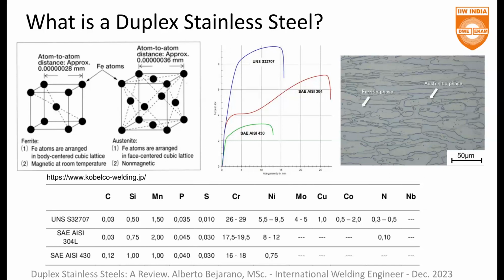And in blue, we have a hyper duplex stainless steel. So we can see here that we have a higher strength in terms of the tension resistance, the ultimate strength. But the percentual elongation is not the best. It's more related with the ferritic stainless steel than the elongation of austenitic stainless steel.